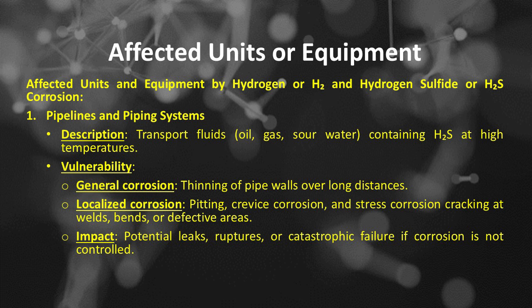Transport fluids, oil, gas, sour water, containing H2S at high temperatures. The vulnerability of high-temperature hydrogen or H2 and hydrogen sulfide or H2S corrosion to the pipelines and piping systems includes general corrosion, thinning of pipe walls over long distances, localized corrosion, pitting, crevice corrosion, and stress corrosion cracking at welds, bends, or defective areas. Impact: potential leaks, ruptures, or catastrophic failure if corrosion is not controlled.